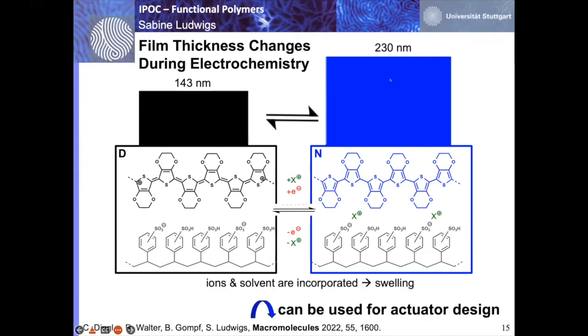And this can be explained by the fact that during these doping and de-doping procedures, ions have to be included for charge neutralization, as I said before. And together with the ion, there's also usually solvent getting included in the system as well. And that leads to overall swelling. So there are a lot of changes in film thickness and in degrees of swelling. And that's the motivation that this can be used for actuator design.